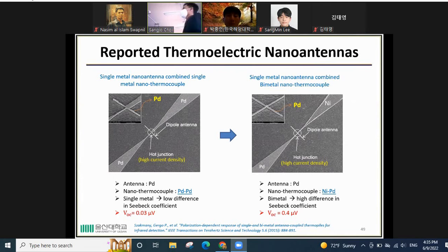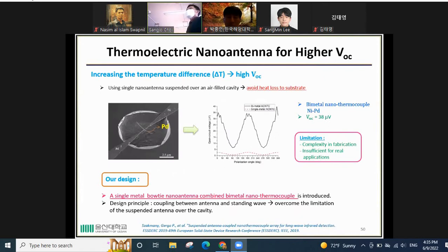So to increase the VOC of the antenna, people use single metal nano antenna combined with bimetal nano thermocouple to increase the Seebeck coefficient. With the nano thermocouple of nickel and palladium, this structure shows VOC of 0.4 microvolts. And also to increase the temperature difference so that VOC is also increased, people use the single nano antenna suspended over the air-filled cavity to avoid heat loss to the substrate. You can see this structure has a higher output voltage, around 38 microvolts. However, this structure also has limitations such as complexity in fabrication and is insufficient for real application.